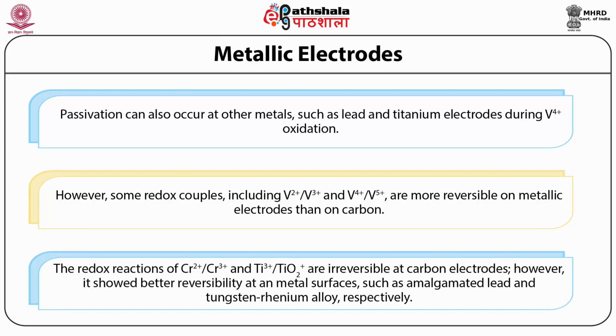The redox reactions of Cr2+/Cr3+ and Ti3+/TiO2+ are irreversible at carbon electrodes. However, they showed better reversibility at metal surfaces such as amalgamated lead and tungsten-rhenium alloy, respectively.